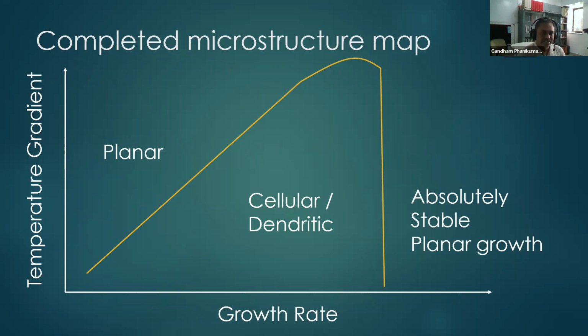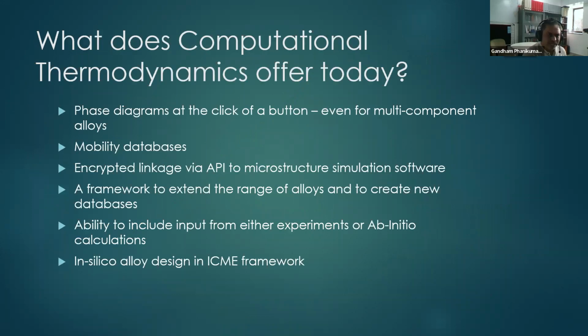So if you take a single crystal base plate, you can have a single crystal growth, and the conditions required for that are known here. You should have a high growth rate and preferably also a high gradient, so that you are staying away from this pyramid of microstructural formation. So you must identify what this value is. Therefore you can operate for getting single crystal during printing. Okay, so that's why we have to understand this in order to take advantage of this knowledge. Today you don't need to worry about this, because there are softwares available. Computational thermodynamics, which gives a very nice way of understanding, is available today.